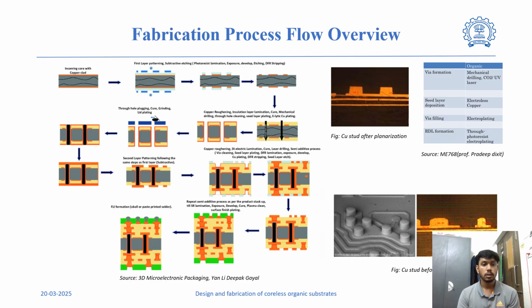The planarization ensures the smooth surface through controlling the lamination, and if needed, chemical-mechanical polishing (CMP) can be used to reduce the surface roughness. Then by drilling or laser ablation, vias can be created in the dielectrics to expose the underlying copper pad and connect the two different layers.